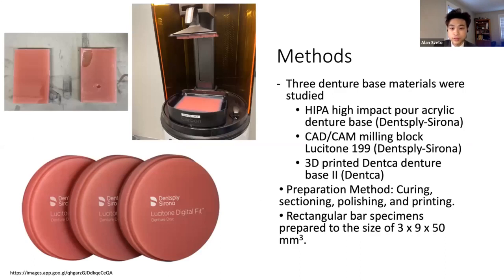So the methods for the study: 3 denture-based materials were examined. First one is HIPA denture base by Dentsply Sirona. Second one is CAD/CAM block Lucitone 199, also by Dentsply Sirona. And the third one is 3D printed Dentca denture base 2 by Dentca. 5 bars per group with a size of 3 by 9 by 50 millimeters were fabricated from each material.